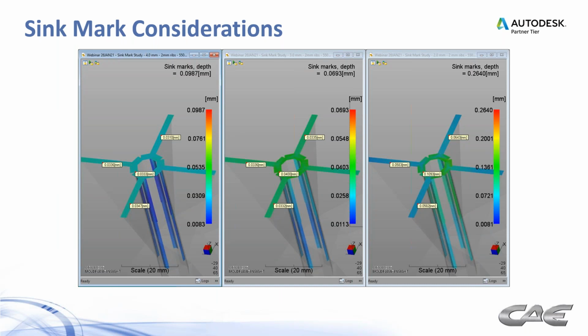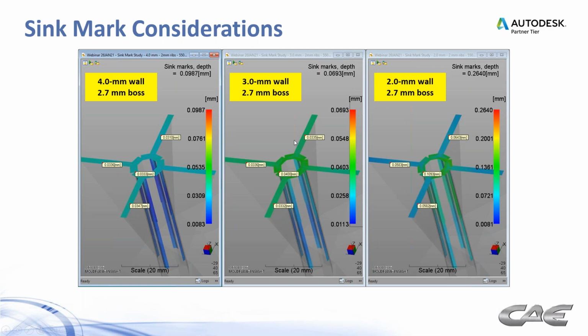I mentioned sink marks earlier. Here's a case where we have a 4mm wall with a 2.7mm boss on it. Reduce that to 3mm, and we start to see a little bit of an increase in the sink mark depth predictions. And then when we go all the way down to a 2mm wall with that same thickness, now you can expect even deeper sink marks. So you've got to pay attention to all those features that attach to the main wall when you start thinning your part out, especially if it's an appearance part where sink marks are not allowed. So you're going to have to start reducing the thickness of the attached features accordingly.